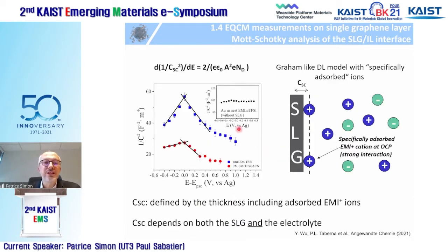However, what is a space charge capacitance on a single layer graphene? It seems to be meaningless because it's a monolayer, single layer graphene. However, remember, if we consider that we have EMI plus cations in strong interaction with a graphene surface, it means that we can propose a kind of Grahame-like double layer model with specifically adsorbed ions. And this space charge capacitance can be defined as the capacitance within this volume, taking into account the volume of the cations specifically adsorbed in strong interaction with graphene.